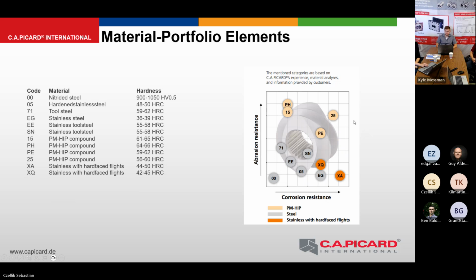And a material which fits very well for corrosion and abrasion is the material 25. It's a good mixture. If you have mainly abrasive wear, we would recommend material 15, or for some zones, material PH, but PH has a problem, it could be very brittle. But PH has one advantage, it has a relatively high cobalt content, and therefore it is heat resistant.